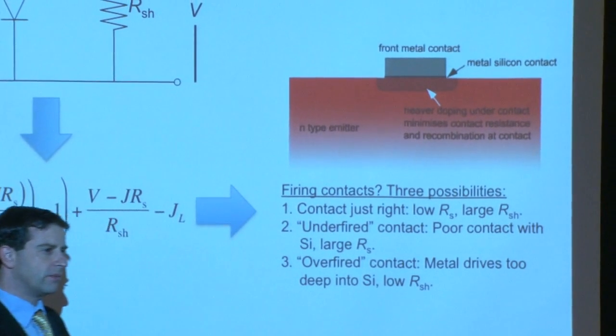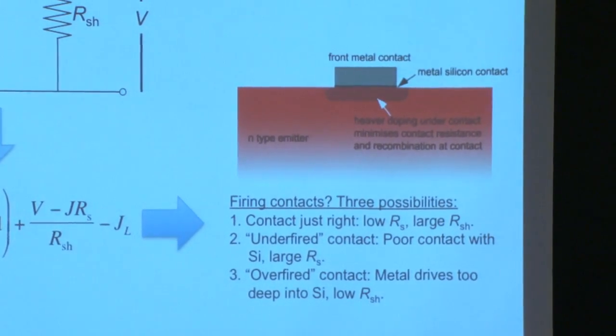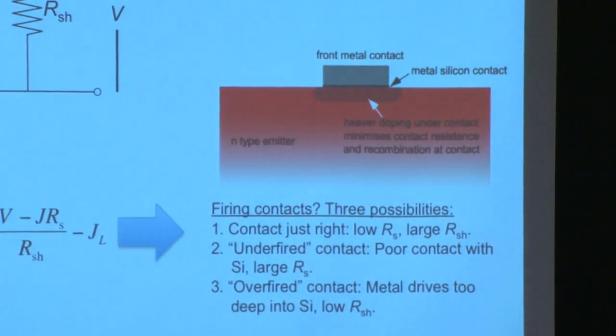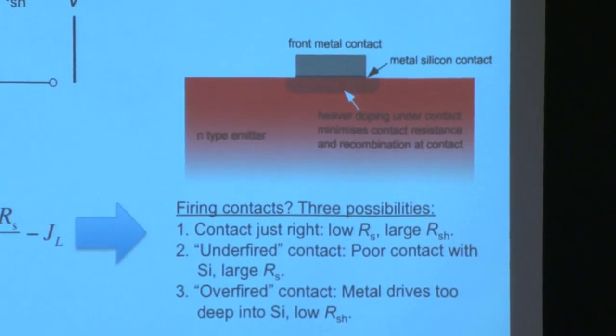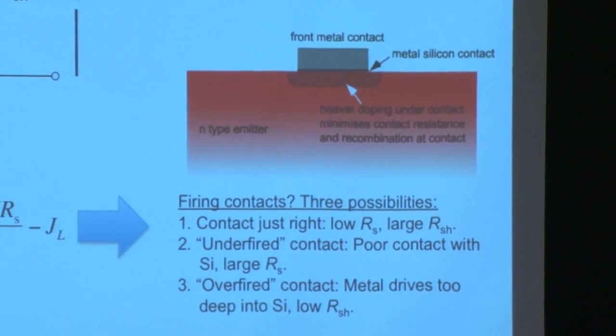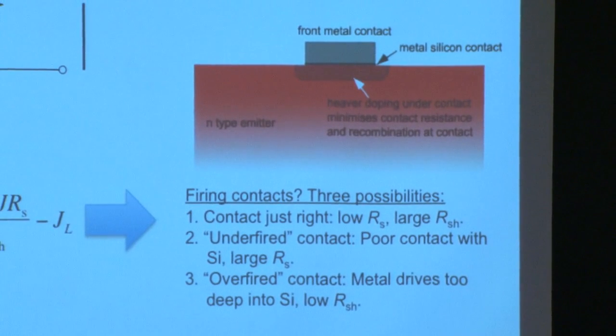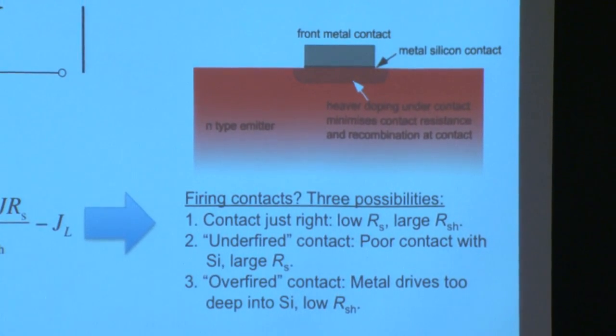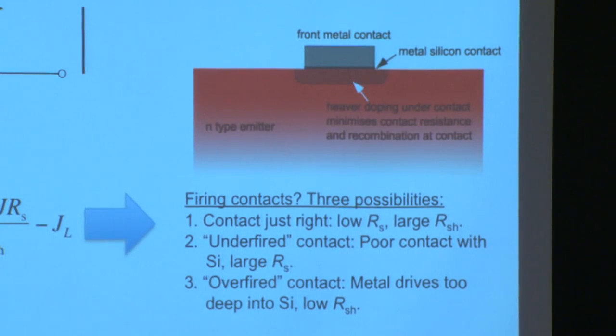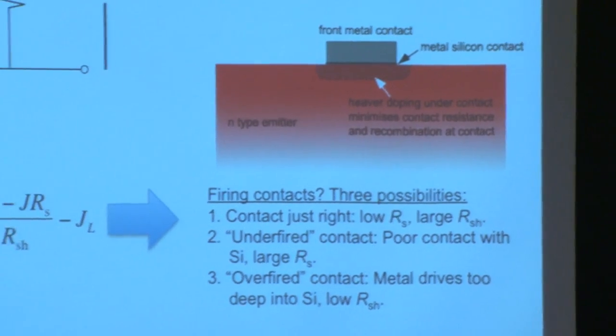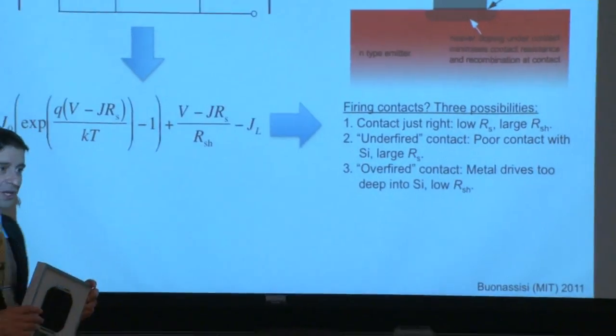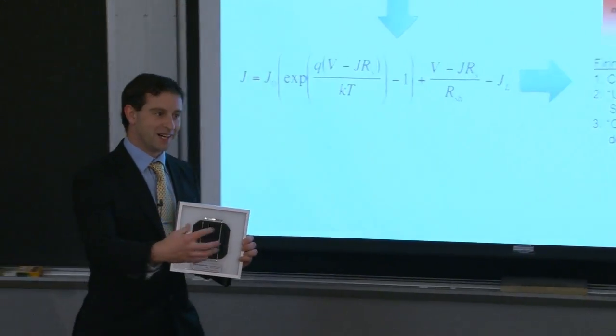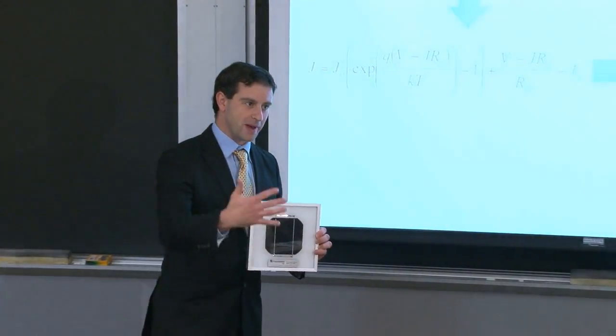The way you typically get an enhanced dopant concentration right underneath the metal. First, let's appreciate the length scales involved here. The width of that contact metal is probably on the order of somewhere between, let's say, 80 and 120 microns, maybe a little more. So at those length scales, we don't need photolithography to really nail a particular location. We're not talking about tens of nanometers. It's really something more macroscopic. So we can do it in a few ways. On the high end, we could use an ion implantation tool to pattern our material with a mask.